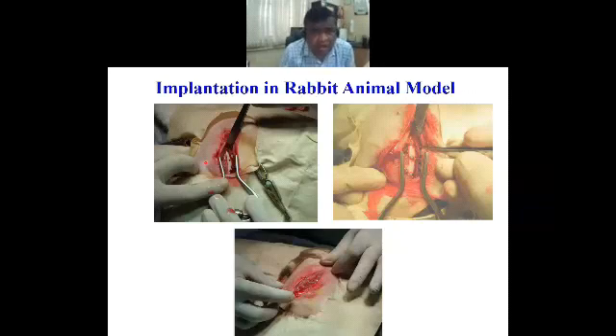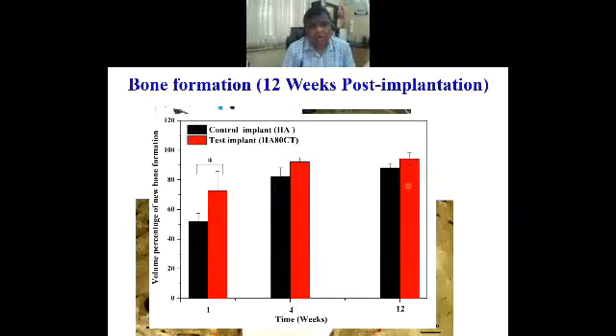We implanted this hydroxyapatite calcium titanate composite in the rabbit femur, and what we found is that the volume percentage of the neobone formed after 1 week, in the case of hydroxyapatite calcium titanate based materials, is much larger compared to hydroxyapatite alone. So what it means is that early bone regeneration is possible or facilitated by electroconductive ceramic.